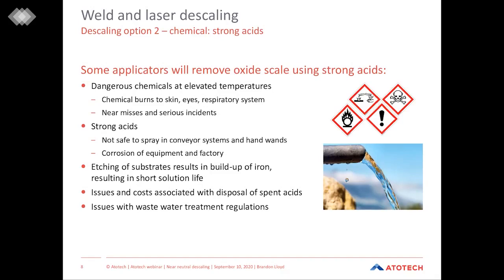These strong acids are not safe to spray in conveyor systems or hand wands. And this is mostly because it exposes the employees to these hazardous chemicals, and it can result in corrosion of the equipment and the factory as well. One of the other issues is that it results in etching of the substrates, which results in a buildup of iron, which leads to a short solution life. Other issues and costs associated include the disposal of the spent acids, as well as a burden on the wastewater treatment regulations.